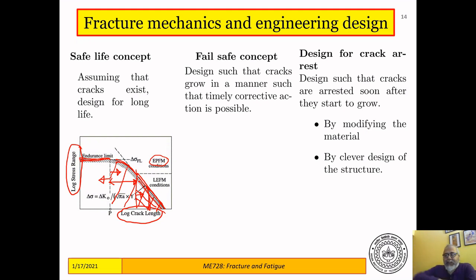Another variant of that is again that okay, small cracks are there, they also grow, but whenever they try to grow, I guess where they are trying to grow from, and then I try to arrest the crack. I try to stop the crack from growing before it causes complete fracture. And this I can do by modifying the material that I'm going to use, and also by clever design of the structures, by adding what are known as crack arresters, which are there in several structures that you see around you. So these are the three major concepts of design based on fracture.